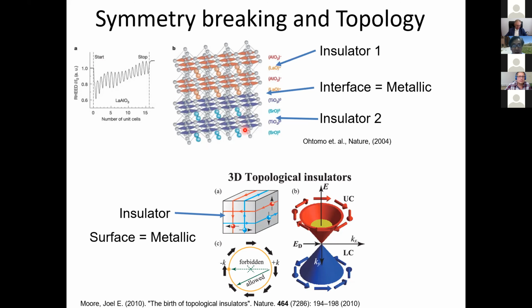In later studies, we found this kind of interface system comes from a topologically protected object. This is explained by the Dirac cone of the surface of the insulator. Here you can see the bulk is an insulator, but a current is observed, and this current is not the normal electric current. This is just spin current. People now know this is the so-called topological insulator, coming from the symmetry breaking of the insulator and the vacuum.